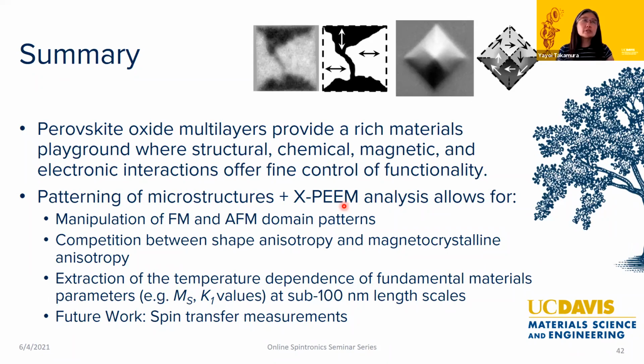PEEM is electrons in and photoelectrons out, which means that even though we have a 100 nanometer, 100 unit cell thick film, the X-rays can penetrate but the photoelectrons can't leave from more than the top 5 to 10 nanometers of the sample. That's one consideration you always have to make with samples in PEEM: you can't put many capping layers on top, because if your capping layer is 10 nanometers thick, you will only probe that capping layer. For our samples, we are only probing the top 5 to 10 nanometers, and we have no idea what the rest of the sample is doing, because the photoelectrons just don't leave the sample from there.